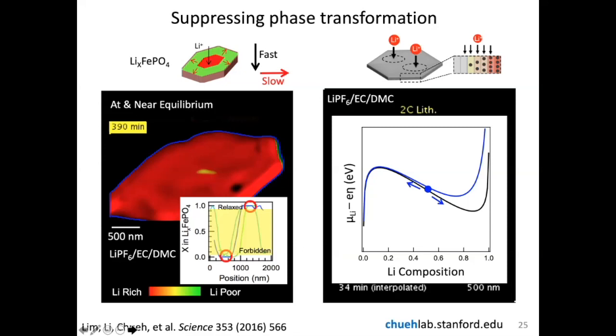So in lithium iron phosphate and any other phase separating system, you have this non-monotonic chemical potential or voltage that causes the lithium to want to partition into lithium rich and lithium poor distributions. But as you apply current, because the overpotential is not fixed with the composition, the overpotential added to the phase diagram actually begins to skew the energy landscape. So rather than having a downhill energy diagram, as you increase current, you actually cause the energy to become uphill. And when this occurs, there's no longer a driving force to cause the lithium to separate.